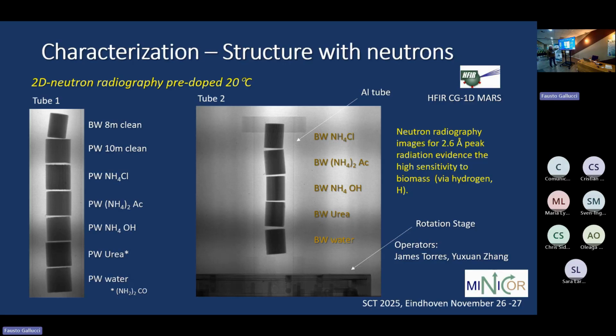So here's a case for raw woods, and you see that there are slight differences with respect to what kind of dopant you use. And with ammonia, you see that it shrinks slightly. This is a piece of beechwood, 8 millimeter, and these are pine wood of 10 millimeter diameter. Here is beechwood correspondingly. Okay. And these experiments were performed at the Oak Ridge National Laboratory, Beamline CG1D in Mars.